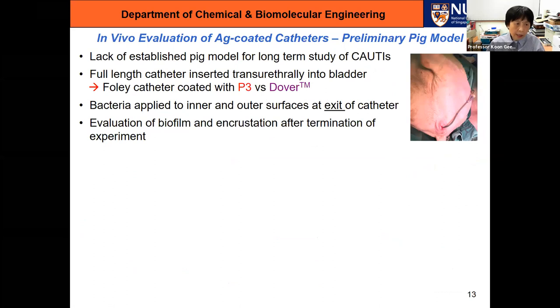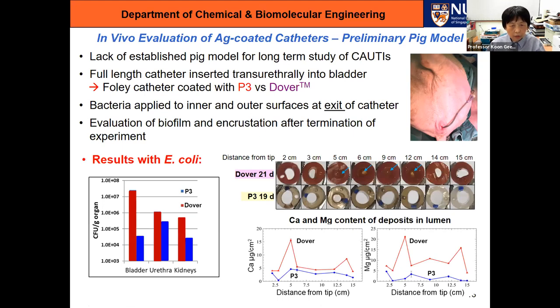So this time, we can compare the P3 with the Dover. And we do not introduce the bacteria into the bladder because we know what's going to happen. So we introduce it on the catheter surface at the exit, and this is how a urinary catheter gets infected. And then we evaluate what happens after a certain amount of time. So this shows the result with E. coli. These are very preliminary results because we didn't have many pigs.